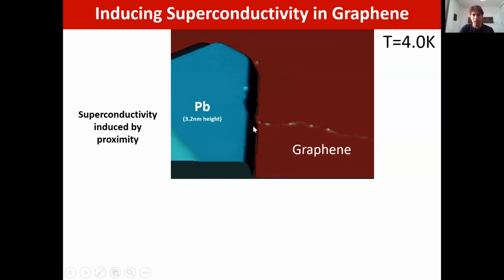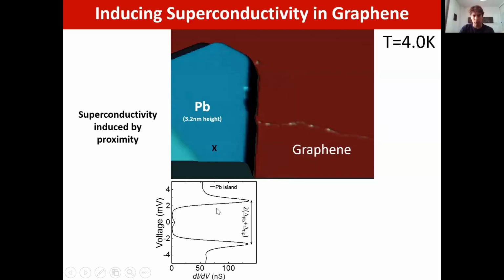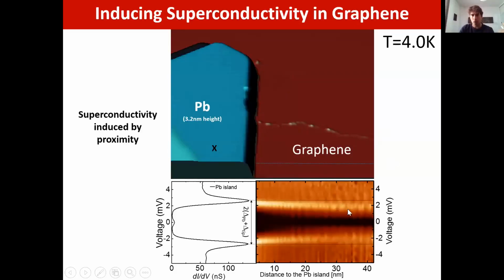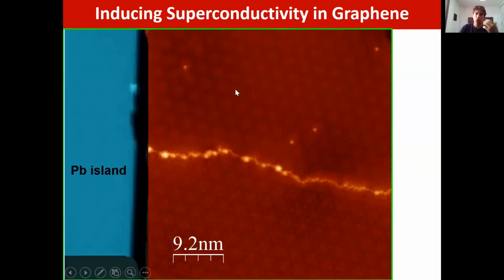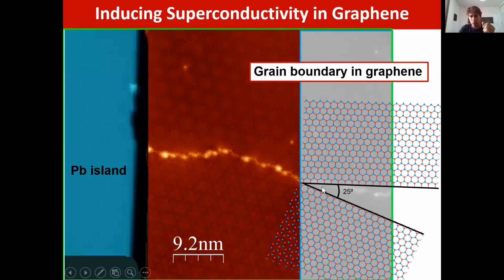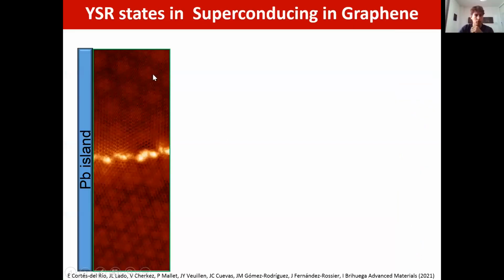So let's now analyze a lead island which is just crossing a grain boundary. First we see that on the lead island we have the superconducting properties. Then we made a line on graphene far away, and we see that graphene is superconducting again, even far away from the island. So we make a zoom of this region to see the atomic resolution on our graphene region, and with this we know that this grain boundary corresponds to two graphene domains that have a different 25 degree orientation, and this is why we have the grain boundary. And now if we analyze even closer this region where we know graphene is superconducting, this is a clearer detail of what we have.